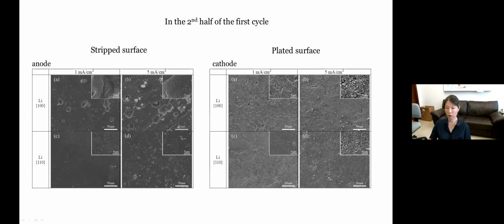But if you think of the plated lithium that sits on the pitted surface, you would imagine these holes may not be filled. Of course, that will rely on three-dimensional SEM images as shown by Shirley in the earlier talks, and which we have the tools to do. Then if the defects are accumulated, you would expect to see a lot of loose layer formed on the lithium 100 in comparison with the lithium 110.